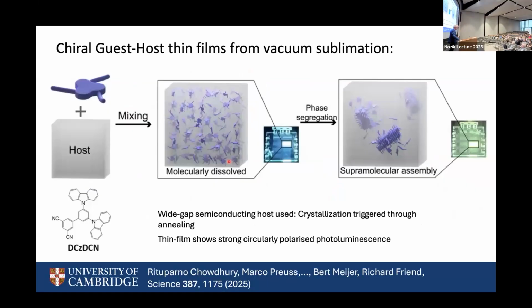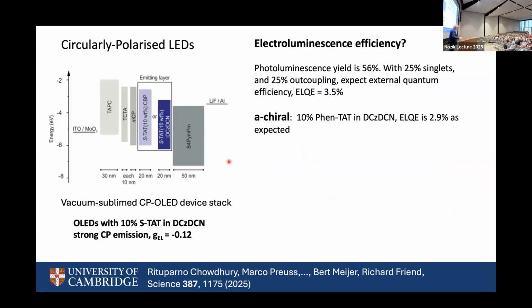But one thing we were able to do was to make LEDs with the structure. There's some details on how we can make thin films, which I'll pass by. But with the OLEDs, we run through what an ordinary structure should do and what we would expect. We have a luminescence efficiency of about 50% or 56%. If you run through how much light we'd expect to get, this is a system where we should lose 3/4 to triplets, just get a quarter of bright singlets.